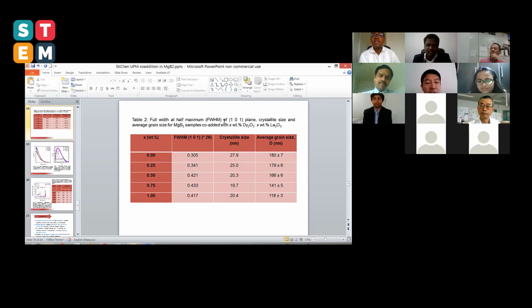Okay, Professor Jack, this is what we believe, because as previously reported, the grain size was decreased by dysprosium or by lanthanum oxide addition because those dopants segregate outside the grain. By having this distribution of the dopants, they prevent or reduce the growth of the grain. This is according to what was found previously, so in our case, we also believe that the same thing happened. And do you think if you increase the density of your samples, you can increase the grain boundary pinning in order to improve the Jc again? Yes, I believe so. Okay, thank you.